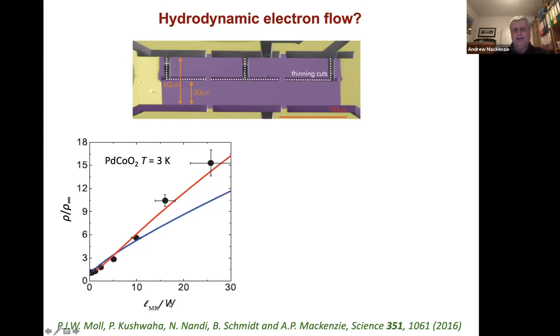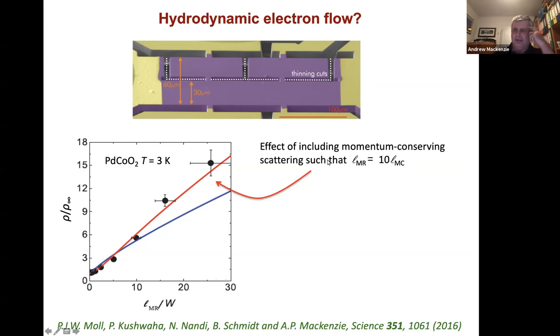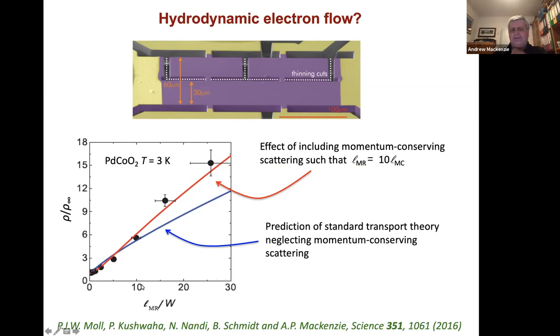And what we discovered was that if we used a theory for hydrodynamic electron transport that involved a very significant contribution to the scattering in the material from putative momentum conserving scattering events, then we got something like the red line, and the red line matched the data rather well. Whereas a standard transport theory prediction of what was going on matched the observed data much less well. So from that, we concluded in 2016 that the reason the transport looked like this was because of the viscosity of the electron fluid, and that we were seeing corrections to standard transport due to electron hydrodynamic effects.